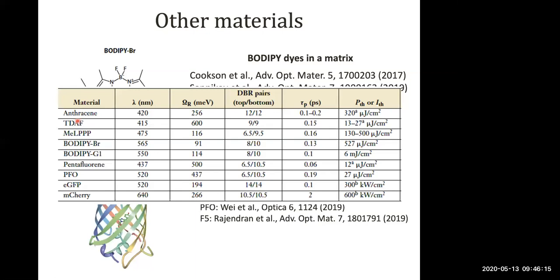So in TDAF, for example, the Rabi splitting is about 600 meV, and we typically are operating in a regime where we have a detuning of maybe minus 300, minus 400 meV. So a little bit more than half of the Rabi splitting away in terms of detuning. And this is really because of the lifetime. So if we approach 0 detuning, the lifetime of the polariton goes down because of the broadening, and we see a very similar increase in the lasing threshold.